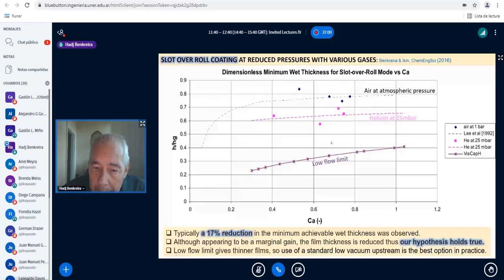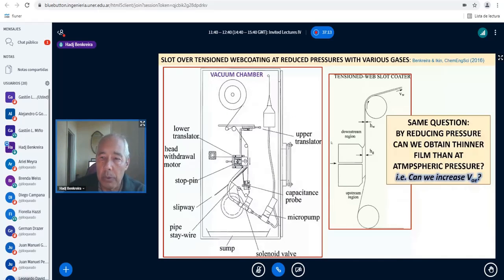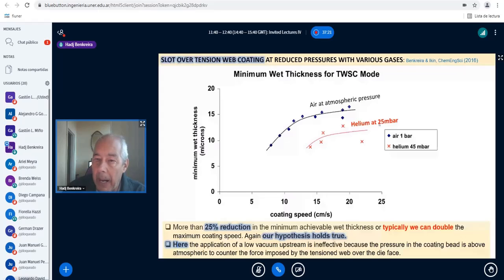And when we look again at slot over tension web coating, we had more success, in the sense that at 25 millibar, for the particular geometry of web tension coating, we could actually obtain a 25% reduction in the minimum achievable wet thickness, or effectively we could double the speed of the operation. So the proof is irrefutable that by controlling the atmosphere of the gas, you can control the gas entrainment speed. And what we propose, the control parameter in here, is the thin film viscosity of the gas.